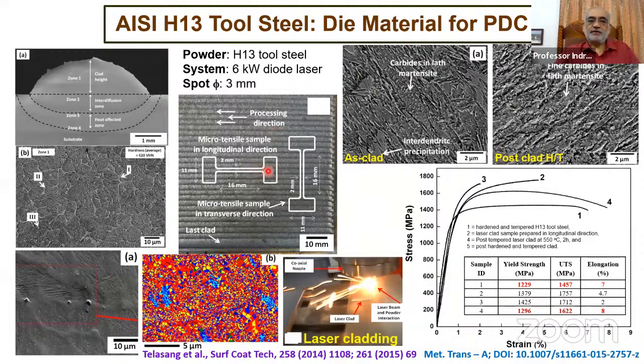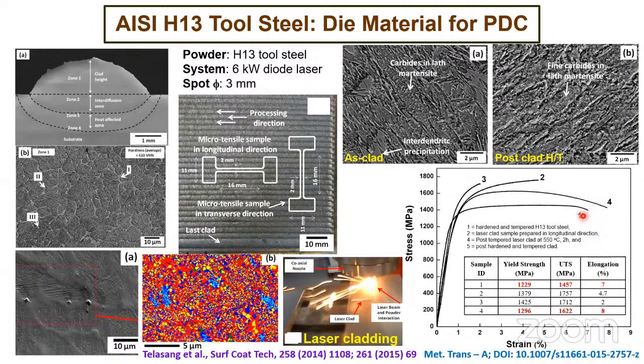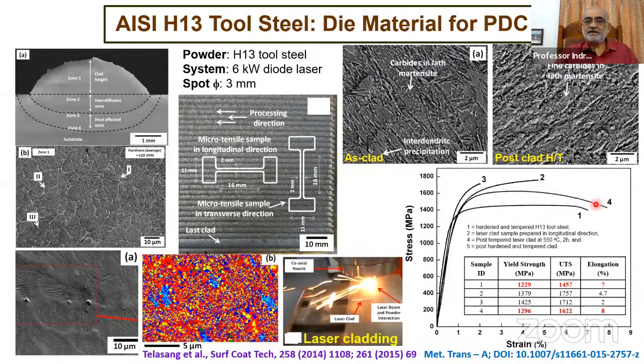And what we showed that the clad layer was actually 3 millimeter thick. So we could easily machine out, very carefully though, some 2 millimeter thick micro tensile components. And if you just look at, without going into all those details, compare curve 1 and curve 4. So curve 1 is the H13 in the pristine condition, and 4 is the result from the clad zone after not only cladding, but also subsequent tempering. And this shows higher strength, yield, tensile, and even higher ductile region, higher deformation region, plastic region. So higher toughness, higher strength, higher longevity of the material of a refurbished component.